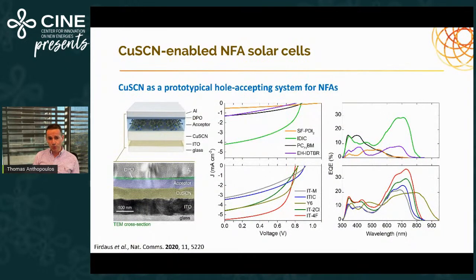We have also been able to use it for basic studies. Again, we went back to the bilayer systems, copper thiocyanate, which is fully transparent and doesn't absorb any light relevant to the solar spectrum. And then we deposit an acceptor layer with different thickness.